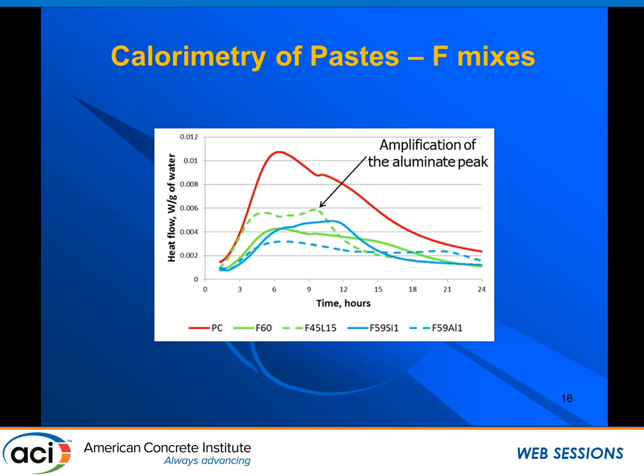So let's see what happens when we put in nano silica and nano boehmite. For the nano silica, the aluminate peak is amplified, but the curve shifts to the right even further, so there's a delayed setting. And for the nano alumina, nothing seems to be happening—the peaks are even lower, and it didn't shift to the right.